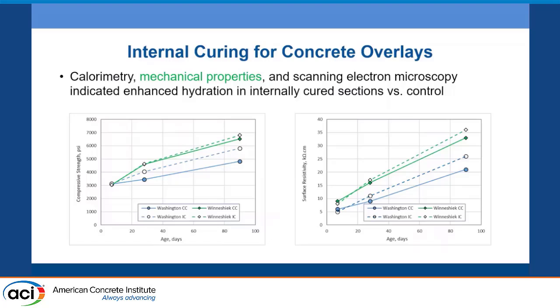They did testing of various mechanical properties, casting samples on site. So what we see listed here on the left, we have compressive strength. Again, the dashed lines indicating the internal curing sections, and they both achieved higher compressive strengths. And again, we actually see the benefit looks like it's greater in the concrete overlay here, at least relative to this other project that was done. I believe that was an 8-inch thick concrete pavement. Same story, the plot on the right there is surface resistivity, so testing cylinders to infer permeability, long-term durability. Again, the internal curing sections were able to achieve greater surface resistivity values.